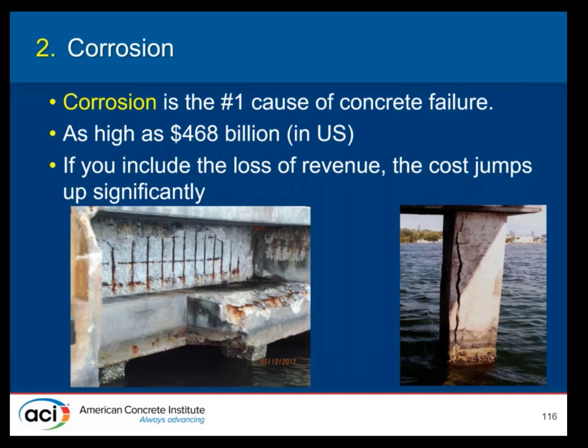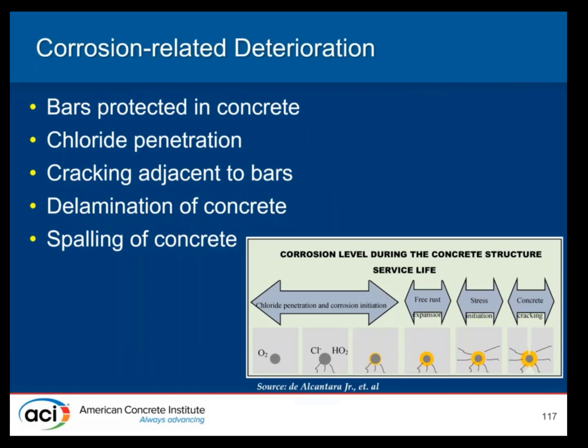So what we're looking at on the left side is a pile cap that supports a seawall that is cracked due to corroded reinforcing steel. And on the right side is a marine pile supporting a dock. The rebar behind this corner expanded and caused the corner to crack. So what's going on? What's causing this damage?